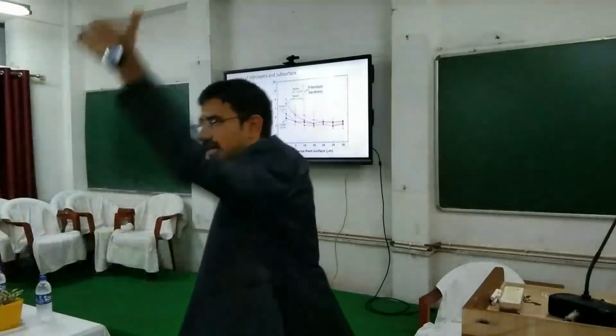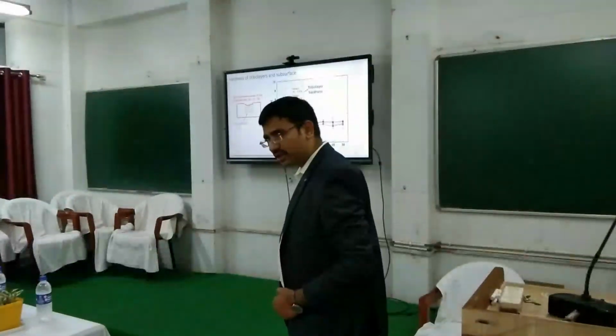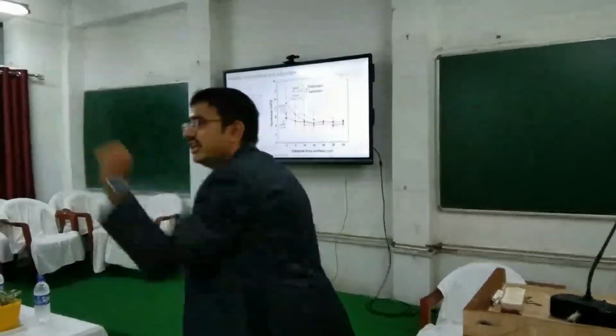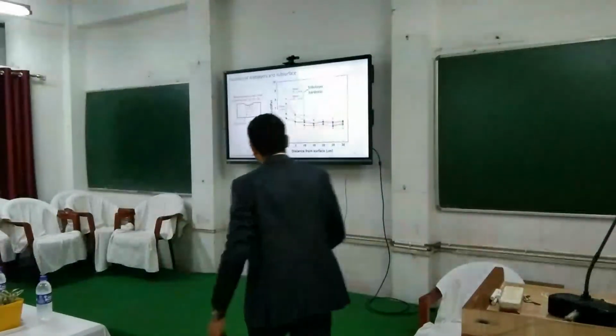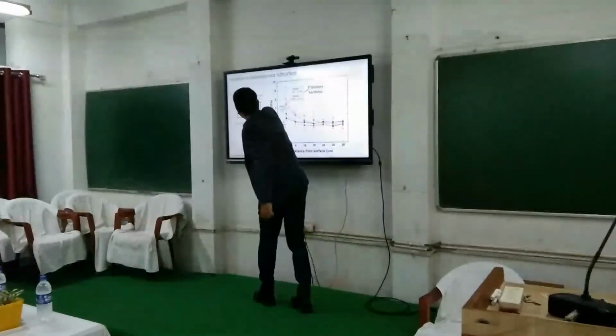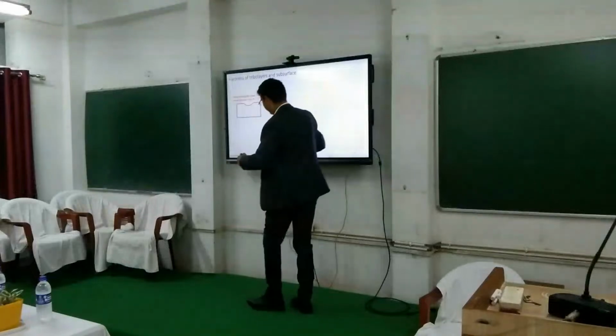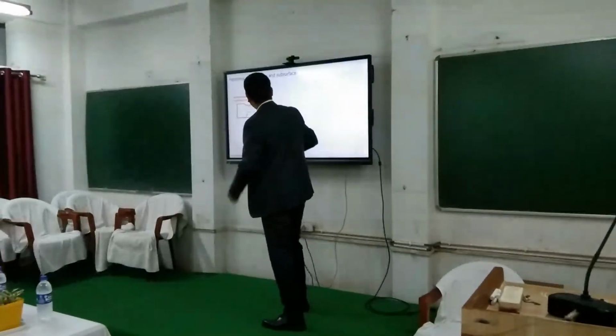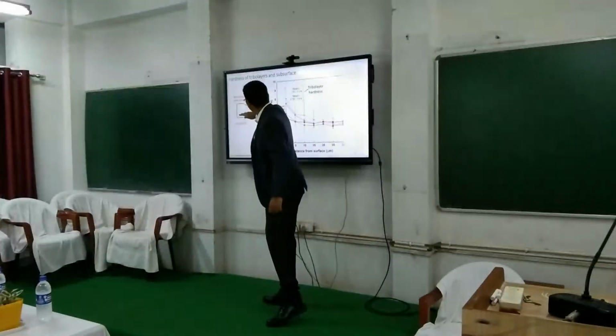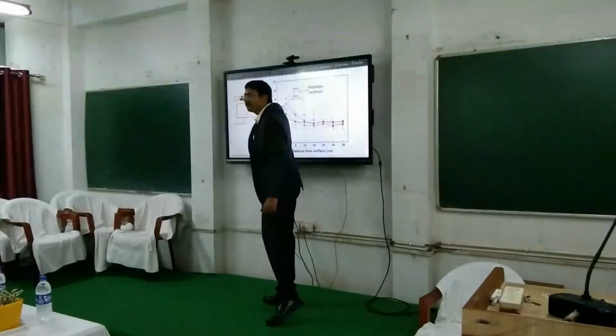So what we did, we cut the cross section of the wear track, okay, and then we did nano indentation. Okay, nano indentation we started. So this is the cross section of the wear track, and then we started to do indents from unworn area to the worn surface, and then we plotted that hardness.